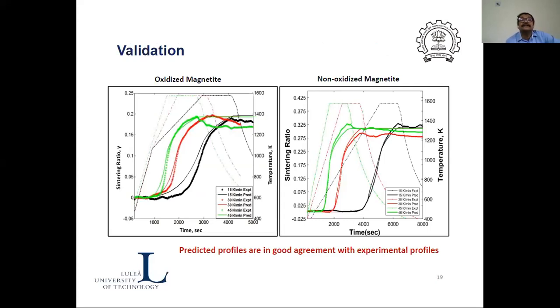And you can see that these are the predictions and these are the experimental results, and it's a very nice match between what we found experimentally and the models. So that way, a judicious combination, a focused experimentation, can give much better information, and it can result in quantitative information.